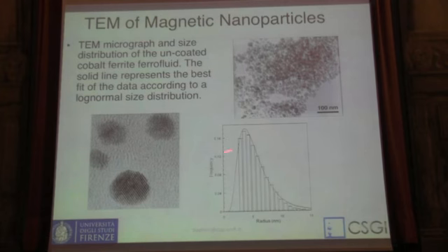So you synthesize and you have to control the size of the particle. You can start from the smallest, which can be 2-3 nanometers, but basically these systems are superparamagnetic, meaning that the magnetism of this system, the responsiveness to a magnetic field, changes according to the size of the particle. And this is a small particle, about 4 nanometers, and you can detect a very crystalline particle. Here there's the ferrite atoms distribution.